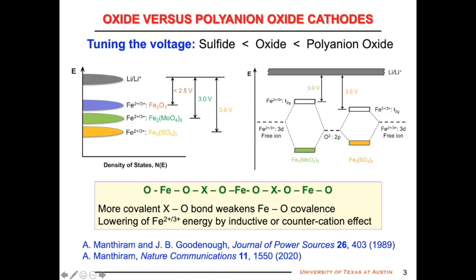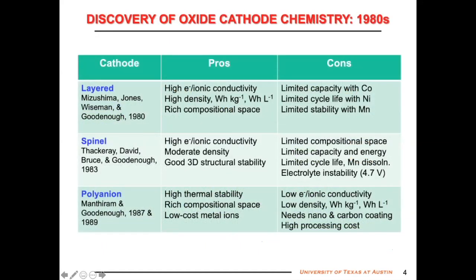In these examples, you go from 3 volt to 3.6 volt from molybdate to sulfate. And in fact, you go from less than 2.5 volt to 3.6 volt when you go from iron oxide to iron sulfate. So this is yet another way of increasing the voltage when you go from a simple oxide to a polyanion oxide. So there are now three major classes of oxide cathodes: layered, spinel, and polyanion family of oxides. And all the three of them were developed by Professor Goodenough's group, started at Oxford, and then also carried out, at least the third part, at the University of Texas at Austin.